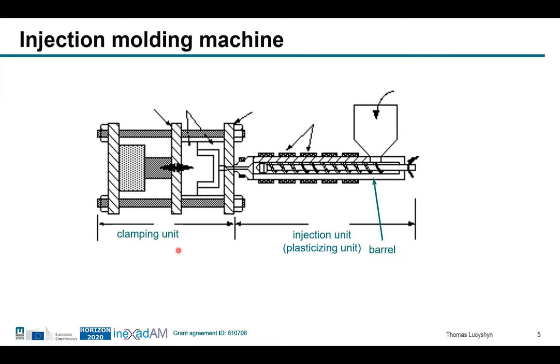So the injection unit consists of a simple metal barrel, which has some heater bands outside to heat the material. Typical processing temperatures for thermoplastic materials in injection molding are in the range of 200 to 300 degrees Celsius. There are materials that go up to 450, but typical polymers are in this range. In the barrel, we have the core part of the injection unit, the screw, which can either move in rotational movement or also in axial movement. Rotational movement for feeding new material and axial movement for injecting the material. That's also why the whole process is called injection molding.